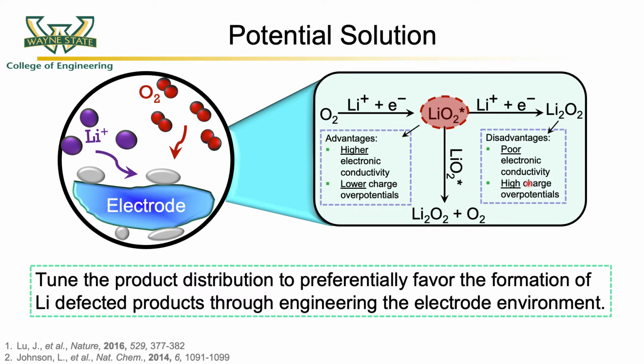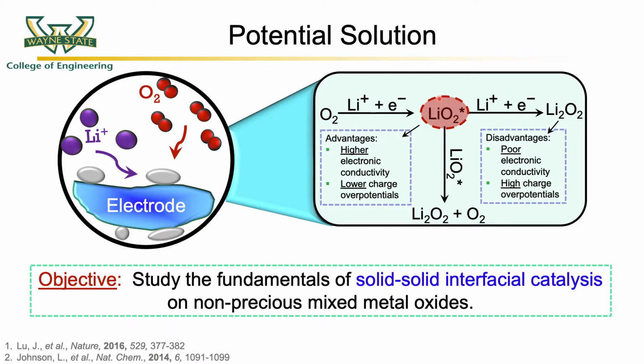In terms of catalysis, this now becomes a selectivity problem where one has to tune the discharge product distribution into the formation of lithium deficient products. Therefore, we set off with the objective to study the fundamentals of solid-solid interfacial catalysis on non-precious mixed metal oxides that guide the selective formation of LiO2.